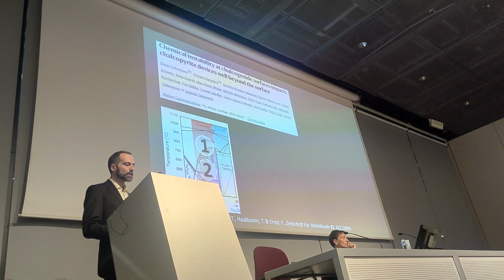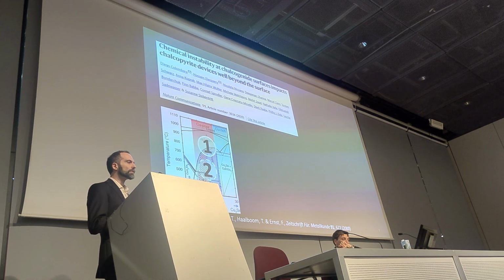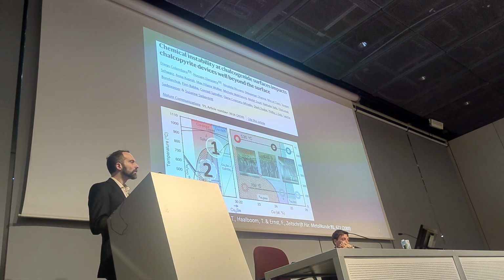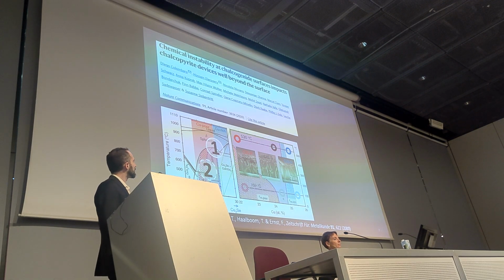So we can grow the material within this range, and if we do that, depending on the relative concentration of copper and indium, we get very different microstructures and different properties of the material. If you grow the material copper poor, we end up with very small grains, you see. As we move to the copper rich, we get larger grains.